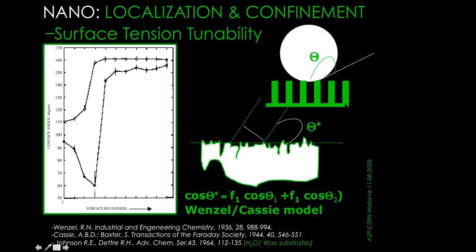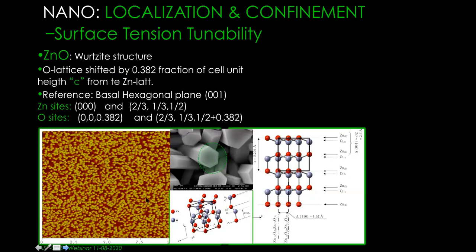We are capable of designing and engineering nanosurfaces with such a kind of narrow nanorods, like this. Well, it is possible to do such with what Bala Ngom has done: he made nanorods of zinc oxide, highly crystalline, as you can see by this AFM, as you can see at the top of these nanorods of zinc oxide. If you go to a large magnification, you will see that they are indeed hexagonal nanorods. We know exactly why they are hexagonal, and so on and so on.